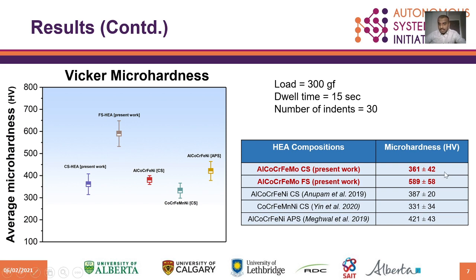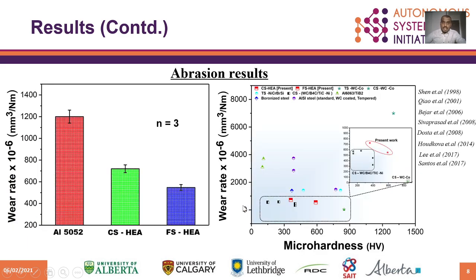The comparative evaluation study suggests that the flame spray molybdenum composition shows 1.5 times better hardness than nickel-based atmospheric plasma spray. This is basically due to the presence of oxides and the formation of BCC phases for the molybdenum-based flame spray composition. Abrasion results suggest that both the coatings exhibited better wear resistance compared to the substrate, where the flame spray shows 24% better than the cold spray HEA, which is basically due to the higher hardness of the flame spray.